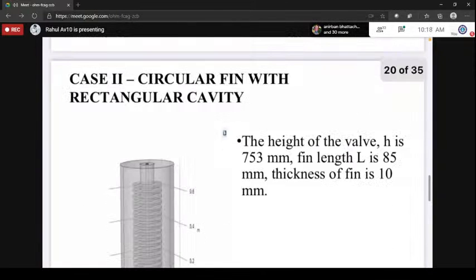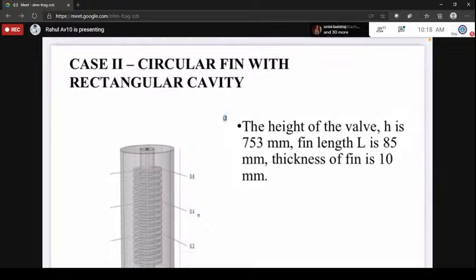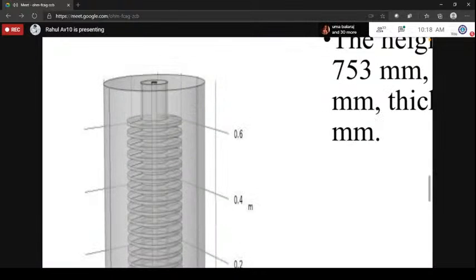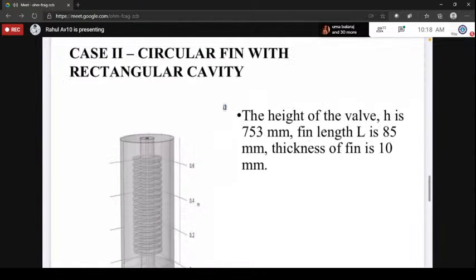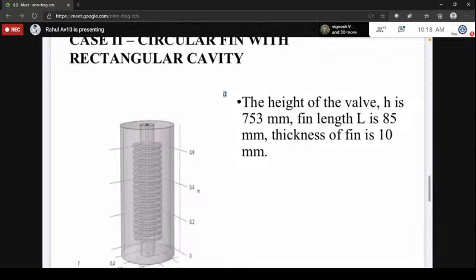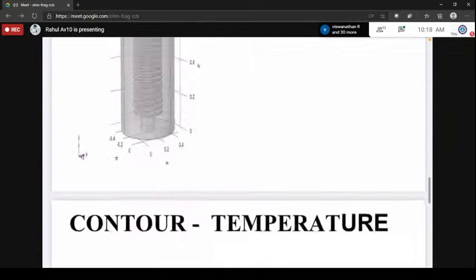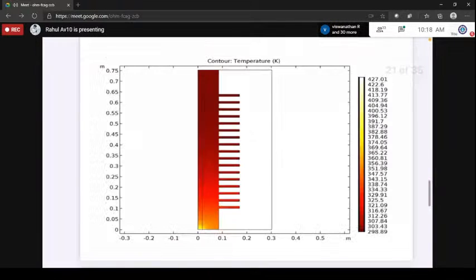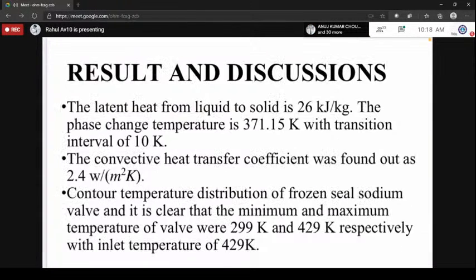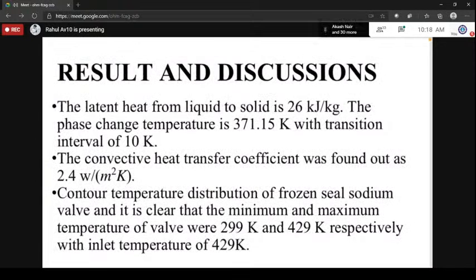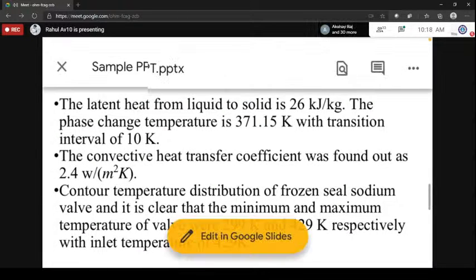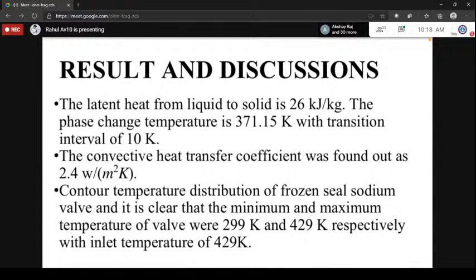And moving on to the second case, which is circular fin with rectangular cavity. It has the same specification as earlier, in case 1. As we move on, the contour temperature is the same. And in these results, we are going to identify that the latent heat from liquid to solid is 26 kilojoule per kilogram, which is the same as the earlier case, and the same phase change temperature 371.15 with transition interval of 10 Kelvin.